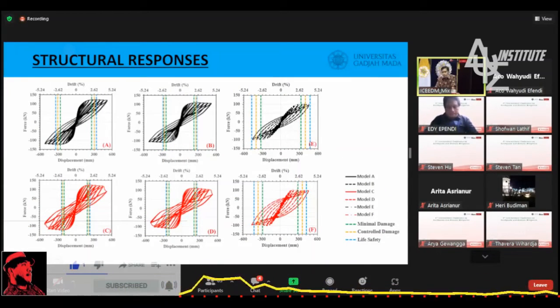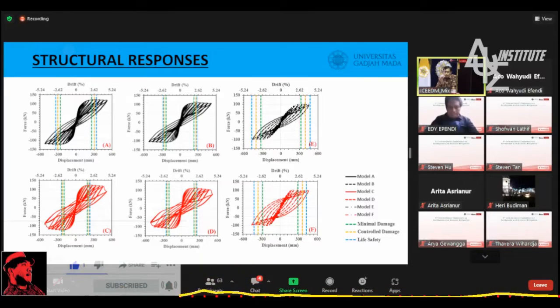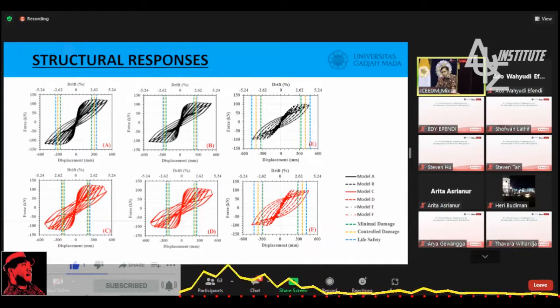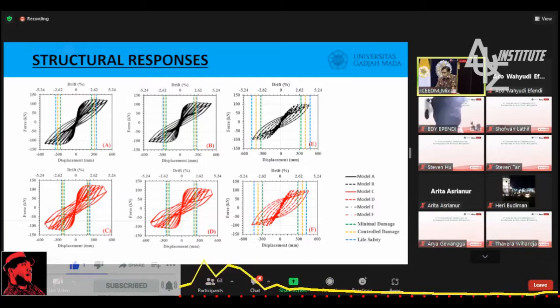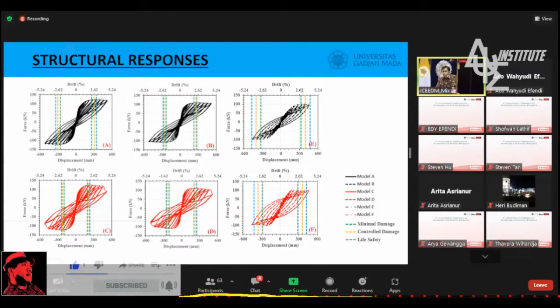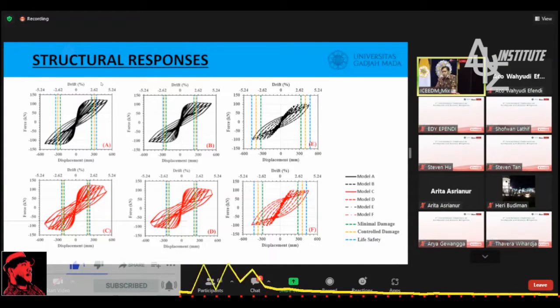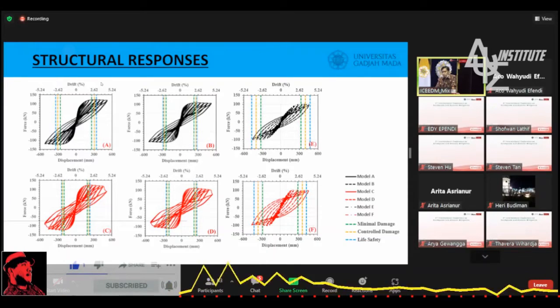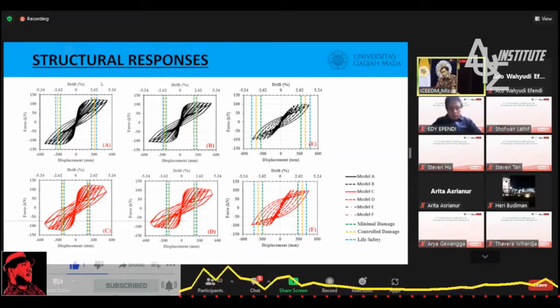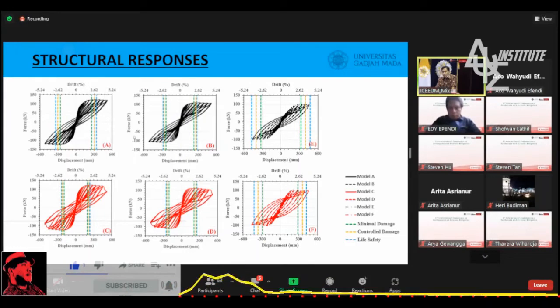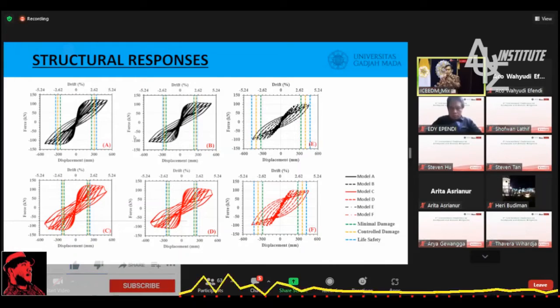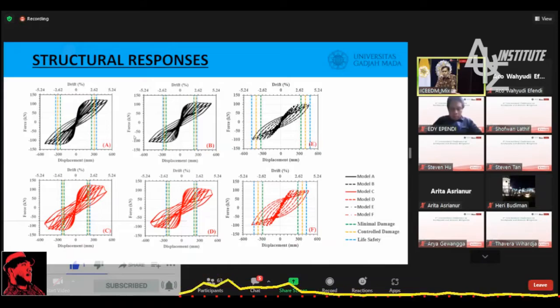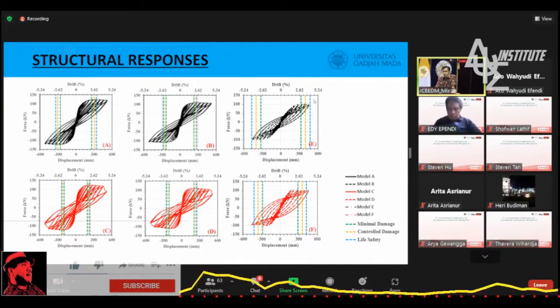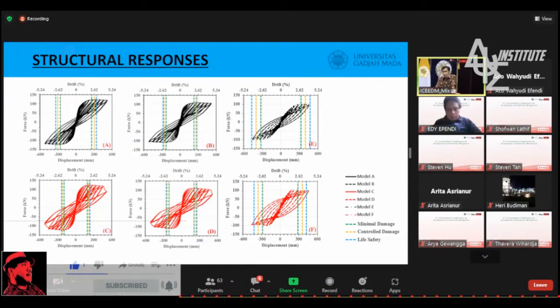And here we can see the characteristic of the hysteresis loops, models A, B, C until F. Models A and B have almost the same hysteresis loop, not so different. So using concrete infill is not so significant in improving energy dissipation. When we compare models C and D, which use fixed restraint without soil structure interaction, we can see larger energy dissipation. However, the lateral strength degradation occurs earlier because of the very rigid, fixed assumption. When we compare to the hysteresis loop of the RC pile, we can see that the RC structure can achieve a plumper hysteresis loop.